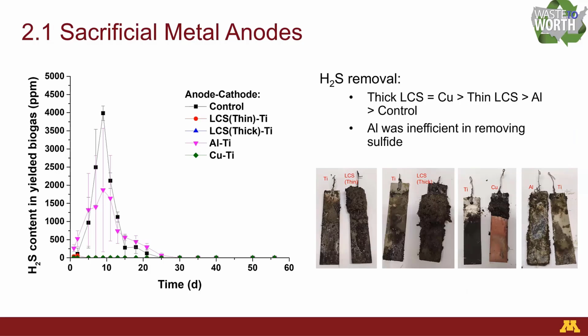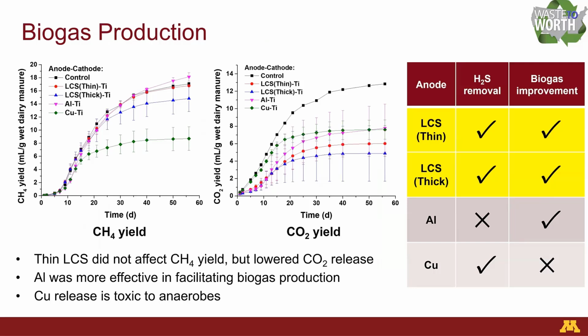test using the sacrificial metal anodes. So we tested low carbon steel, LCS, aluminum, Al, and copper, Cu, against the titanium, Ti, cathode. After the test, we can see low carbon steel and copper removed almost all of the hydrogen sulfide, but aluminum was actually ineffective in removing the sulfide. Then we examined the biogas production as well. Because the manure will be pumped to the digester later, we do not want our anode to reduce the biogas production after removing the sulfide.